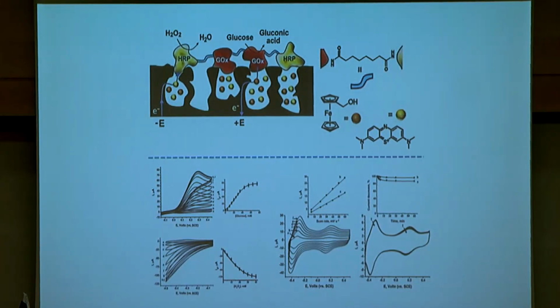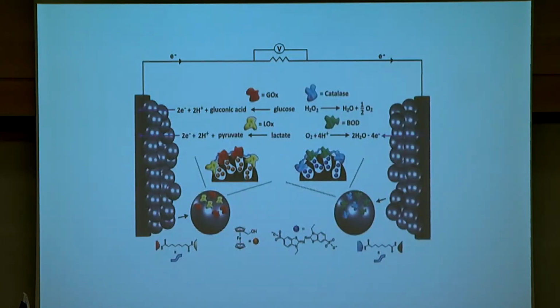If we apply a potential on this mass of carbon nanoparticles, you can see that we can effectively oxidize glucose, mediated by the ferrocene embedded in these pores, or reduce hydrogen peroxide with the methylene blue by the horseradish peroxidase enzyme. And these electrodes are stable for weeks and months without any leakage of the components or deactivation of the system. Once we had this as a potential use for sensors, and we were able to contact the enzymes with the bulk electrode surface, we applied this concept to develop biofuel cells.